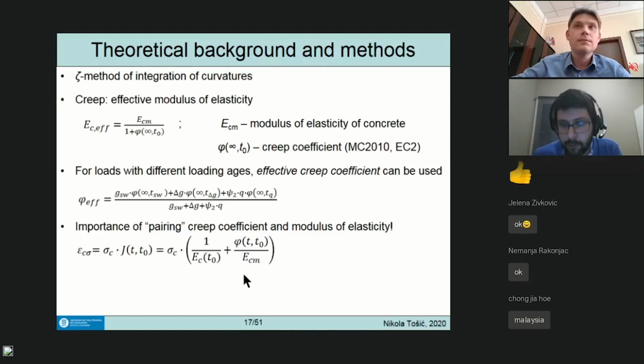In the model code formulation, it is like this: 1 over the modulus of elasticity at the time of stress application, so ECT0. If it's loading at 14 days, this is the modulus at 14 days. Then it's the creep coefficient divided by the modulus of elasticity at 28 days. This creep coefficient in the model code is supposed to be calculated according to the model code model.